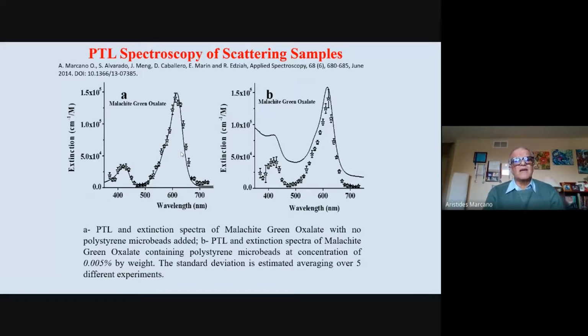We also did an experiment back in the US in 2014. I had some visitors from Mexico, and another student from China actually. We did this experiment with scattering samples. We have some dyes like this, the same malachite green oxalate, and then we add some latex microspheres. These microspheres have some scattering. If you don't have microspheres, you get a very good coincidence between thermal lensing and absorbance. So you see excellent coincidence. But if you have the microspheres, the absorbance produces some big difference between thermal lensing and that. It means that we can actually estimate the scattering quantum yield of the sample, and that's what we did.